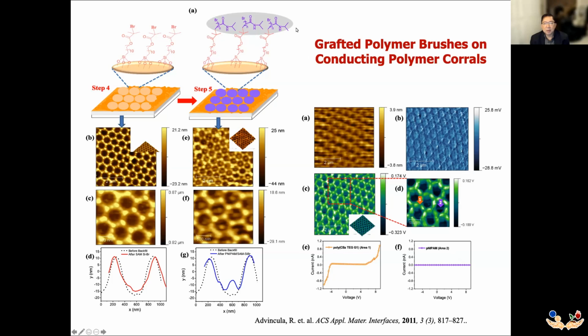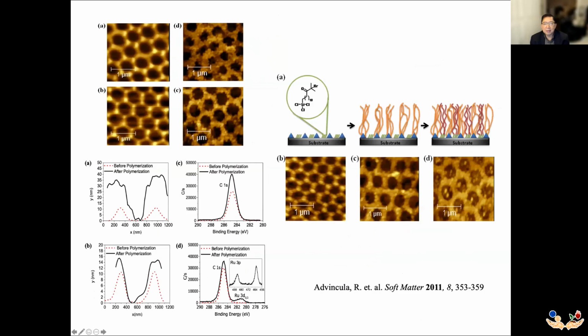And in fact, this polymer is even swellable, as I've shown earlier in the case of polyNIPAM. And the conducting AFM here shows that the ridge pattern with the false green color has a heterojunction behavior. On the other hand, inside the pattern, which is the blue hole where we grafted the polyNIPAM, they're basically insulating. Now, we have done many chemistries on this.